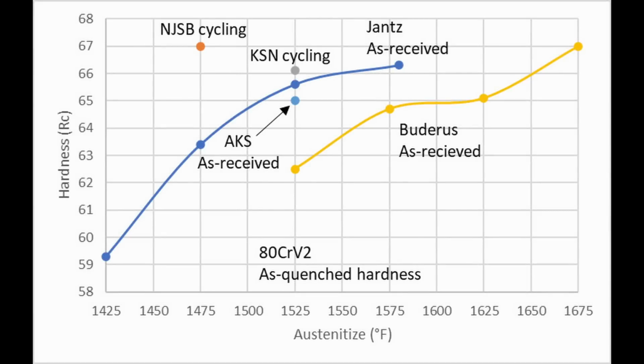Some steel manufacturers will have a coarser starting structure than others, leading to differences in how the steel responds to heat treatment. In my prior study on 80CrV2, I found that one steel manufacturer's steel needed significantly higher temperatures than the others to achieve the same hardness. So here you can see the Buderus material is softer for a given austenitizing temperature than the steel labeled Jantz or AKS, which are steel suppliers getting steel from somewhere other than Buderus.